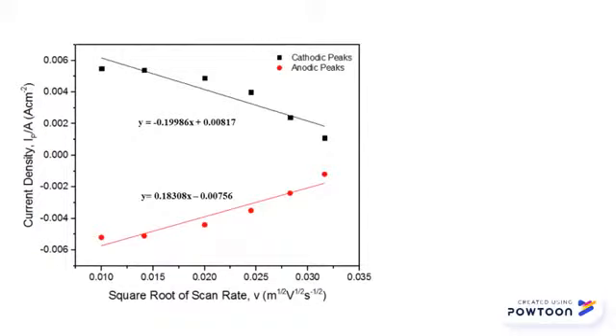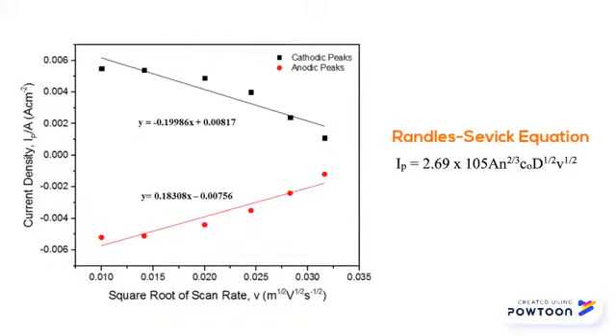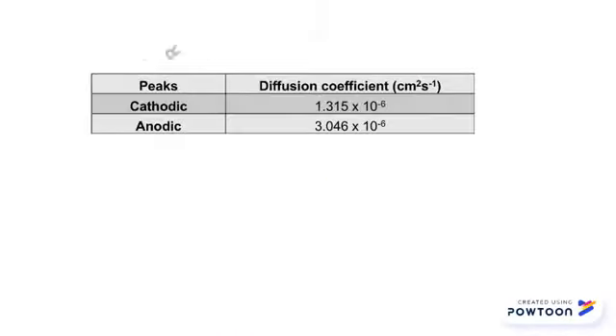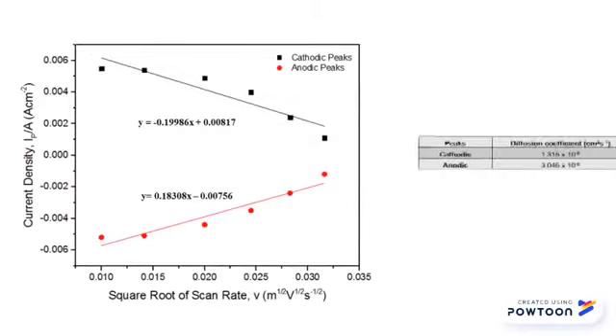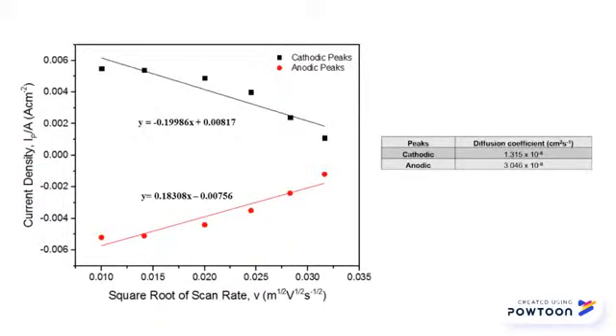To further research the electrokinetics, the lithium diffusion coefficients of the LVO electrode can be calculated by using the Randles-Sevcik equation. The diffusion coefficients of the Li ion in the LVO were calculated as 3.046 and 1.315 times 10 to the power of -6. The anodic process is higher than cathodic. That indicates that the diffusion coefficient of lithium deinsertion is higher than that of lithium insertion. A higher value of the diffusion coefficient means a greater ability of the lithium ion to diffuse in and out of the system. So, a higher diffusion coefficient is more beneficial to the process.